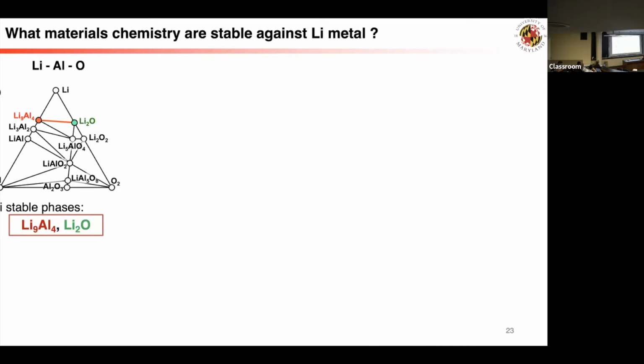These things are required reading for materials students. So for you here, lithium metal is at the corner here. This basically gives all the compositions in the map. All of these form a line, what we call a tie line, with lithium, and those are stable with lithium. So among this space here, only lithium oxide and this lithium aluminum alloy are thermodynamically stable with lithium metal.